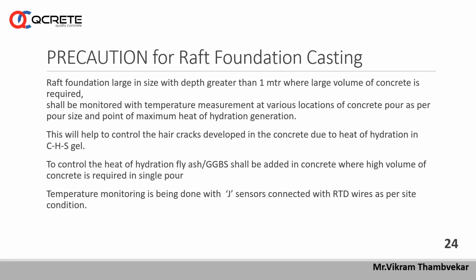Secondly, precautions for raft foundation casting. For many high-rise buildings or industrial buildings where a raft foundation is there, with larger size and where depth is quite big, that is above 1 meter, 1.5, 2 meter, 3 meter. In Mumbai, for high-rise, we have seen some raft foundation depths of 2.5 meter up to 3 meter also, and it's not possible to make concrete in one stroke for all this volume, because the volume of concrete is very high. So concrete is poured in different stages, or at site some pockets or areas are prepared to provide the concrete for this raft, as the volume is very high.